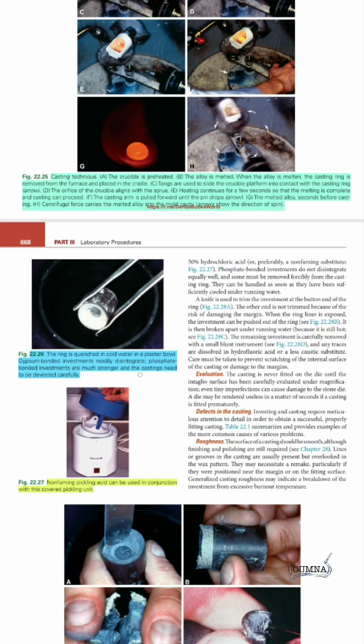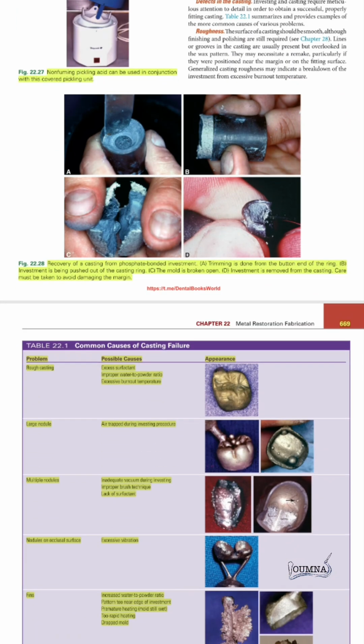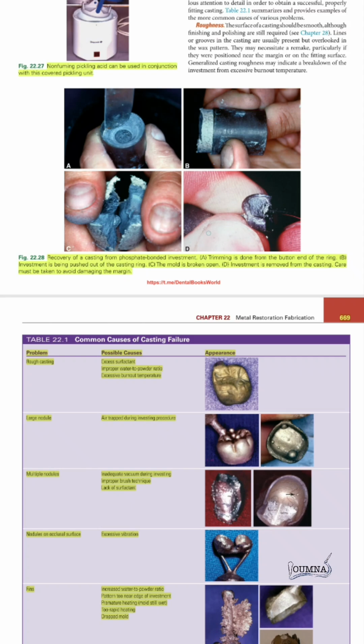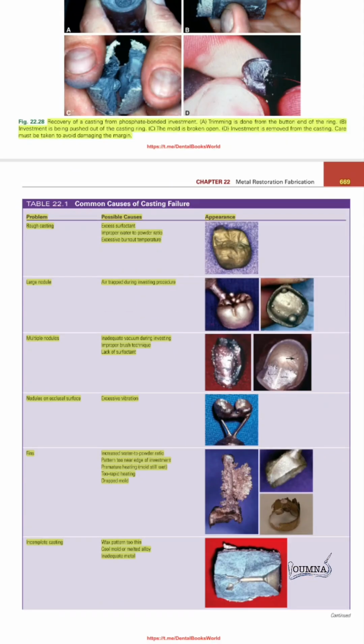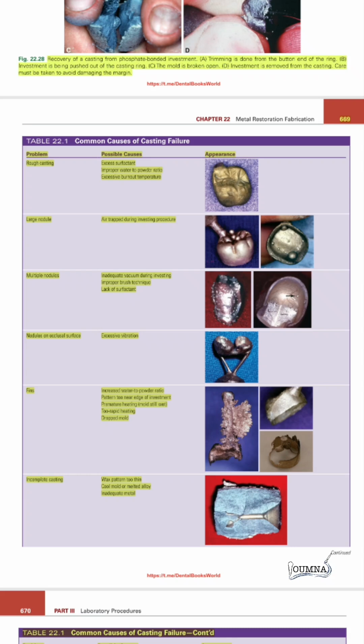After that, it is cooled in water and it is opened out to get the casting inside. One of the common causes of failures, for example, if we got a rough casting, it is due to excess surfactant or an improper water to powder ratio or excessive burnout temperature.